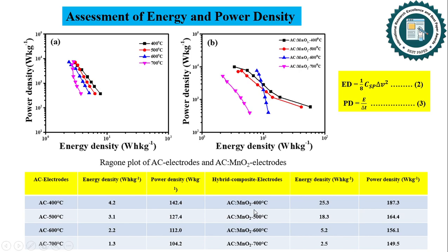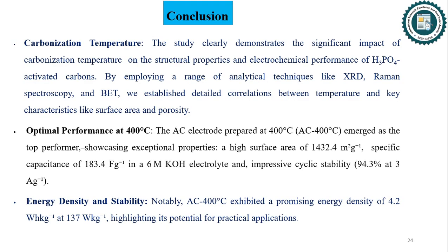So here the AC MnO2 400 degrees centigrade showed significantly higher energy density of 25.3 watt-hour per kg compared to AC 400 degrees centigrade, emphasizing MnO2 synergy. Both AC 400 degree and AC MnO2 400 degree centigrade demonstrated exceptional energy density and power density values, promising for energy storage applications.